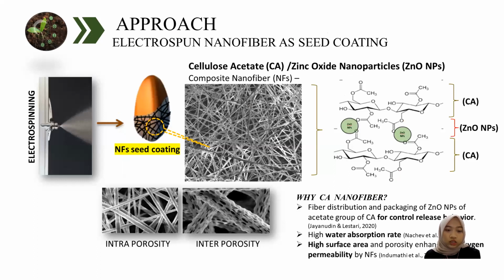Okay, nanofiber here has intraporosity and interporosity. Intraporosity is within the fiber, and interporosity is between the fibers. This projects the enhanced oxygen permeability of the nanofiber seed coating, which favors seed germination. And following here, in the molecular structure of the cellulose acetate, zinc oxide is bound to the acetyl group of the cellulose acetate, forming a complex structure, which is a packaging of the zinc oxide that we are going to use. This eventually will produce a controlled release behavior of the seed coating for seed germination. The cellulose acetate nanofiber also has a high water absorption rate and high surface area due to the nanometric scale size.